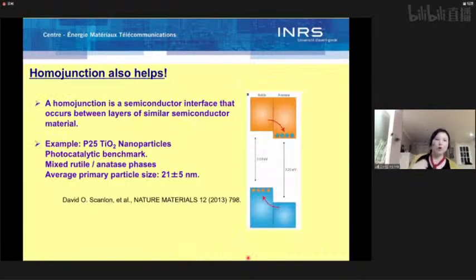In the next example, I would like to show that a homojunction can also help with broadband photocatalysis. By definition, a homojunction is a semiconductor interface that occurs between layers of similar semiconductor materials. The most famous example is the P25 titanium dioxide nanoparticles, which have been used quite a lot as a photocatalytic benchmark. P25 has two phases of titanium dioxide nanoparticles, rutile and anatase, and the catalytic activity is much higher than pure rutile and pure anatase nanoparticles. It's because these two phases form a kind of type 2 junction, which can help with charge separation, suppress charge recombination, and thereby help with photocatalysis.